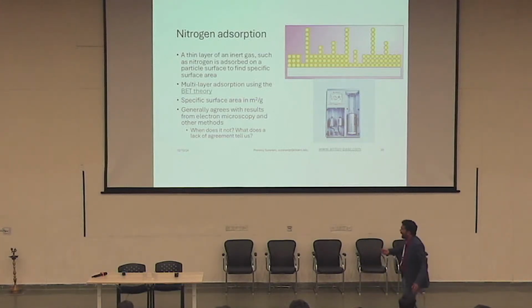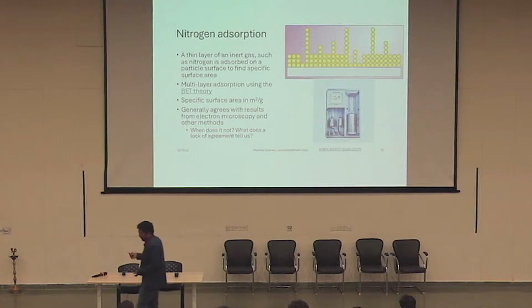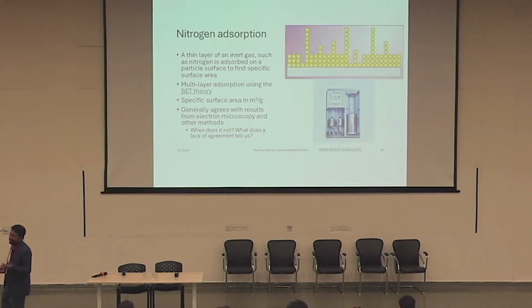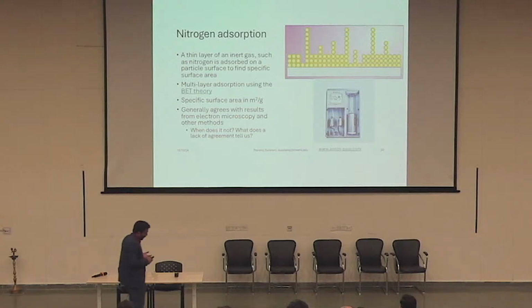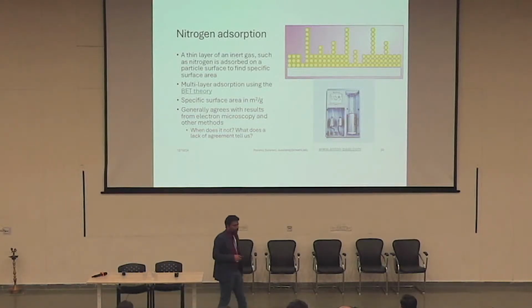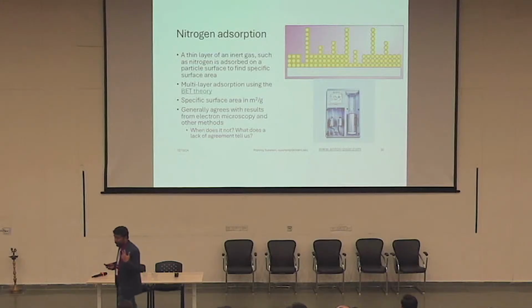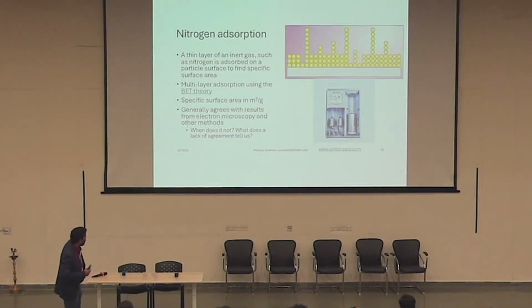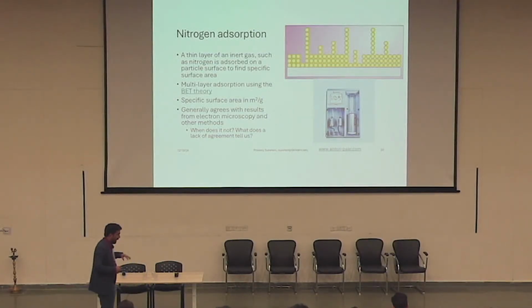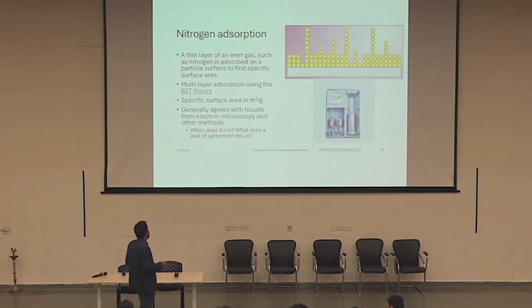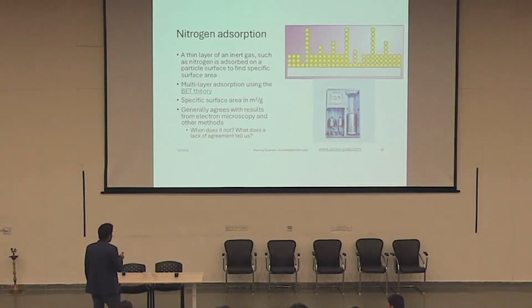Because it's inert, right? If this thing is chemically interacting with your surface, what are you going to measure? You've modified your surface. So you use typically inert things. Nitrogen is one, but it can also be various other things, argon, etc. And because we use nitrogen, of course, there's a lot of sample preparation. This has to be done at low temperature. We have to clean the sample. We have to dry it. All of that sample preparation can be quite complex. So we get the specific surface area in meters square per gram.